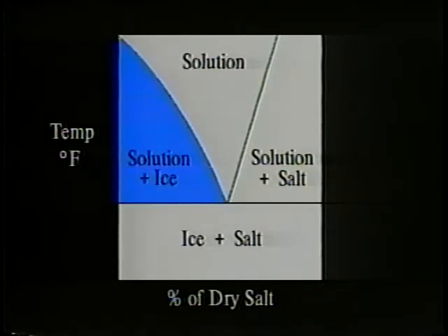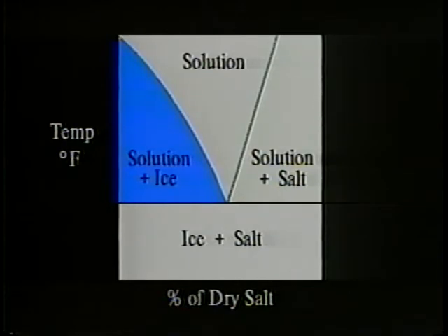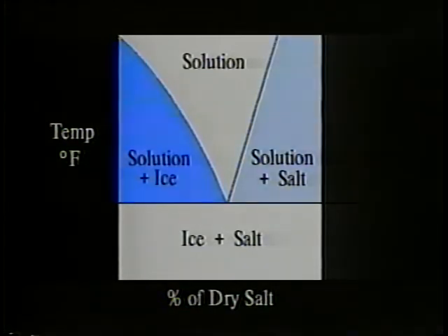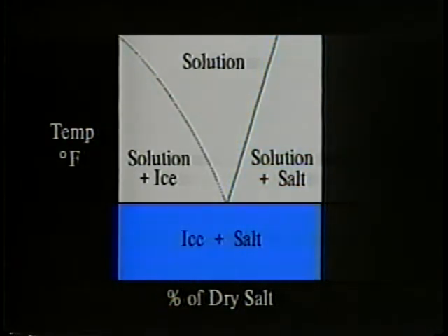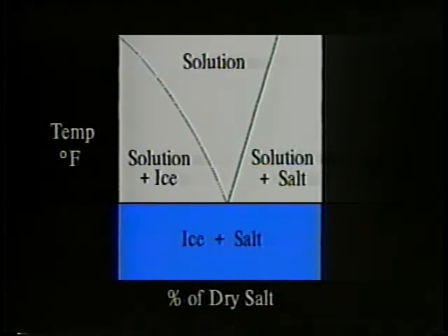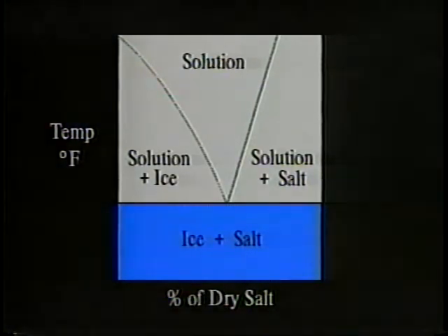Below the left part of the solid curve, there is not enough dissolved salt to melt ice; in fact, some of the solution freezes. Below the right part of the solid curve, some of the salt that is already dissolved precipitates out. Anywhere on the plot below the lowest temperature on the curve — called the eutectic, the solution with the lowest freezing point — no amount of applied salt will melt ice and existing salt water will freeze.